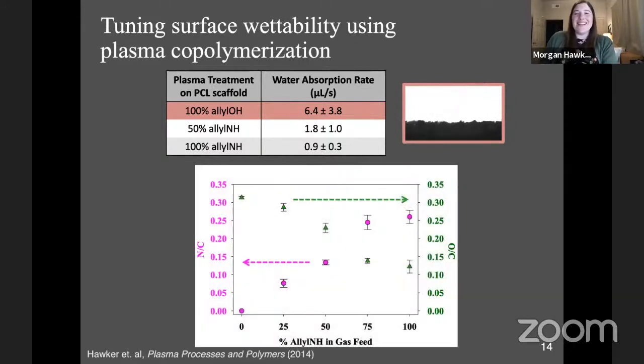I did some chemical analysis of the surface using a technique called X-ray photoelectron spectroscopy. And what this technique is used for is to measure the composition of the outermost surface, the top 5 to 10 nanometers or so, in terms of the elements present on the surface. So what we're looking at here on the left hand y-axis is the nitrogen to carbon ratio, and on the right, oxygen to carbon. Now the x-axis shows percent of allylamine in the gas feed. So over here we have 100% allylamine, and over here we have 0% allylamine and 100% allyl alcohol, and then some intermediate compositions as well.